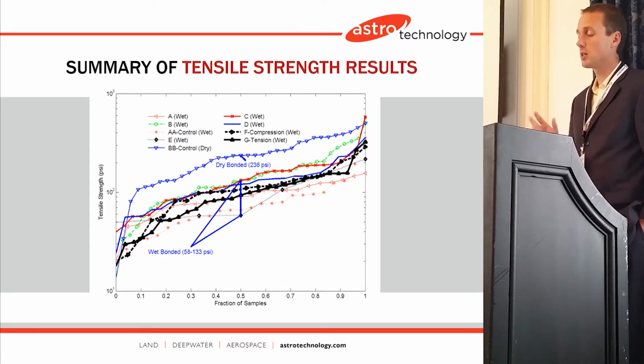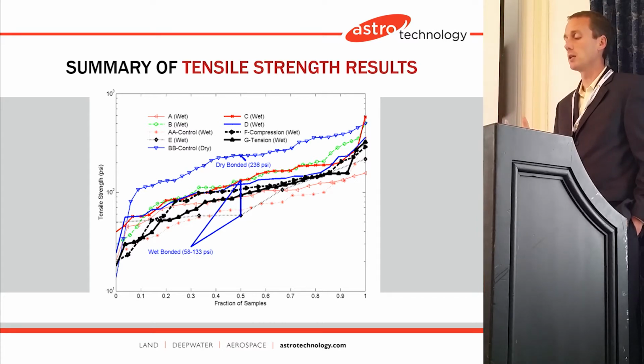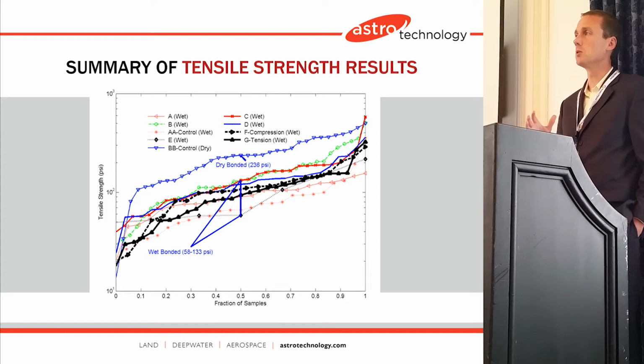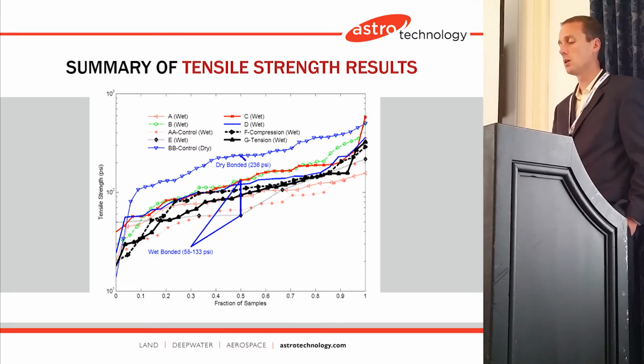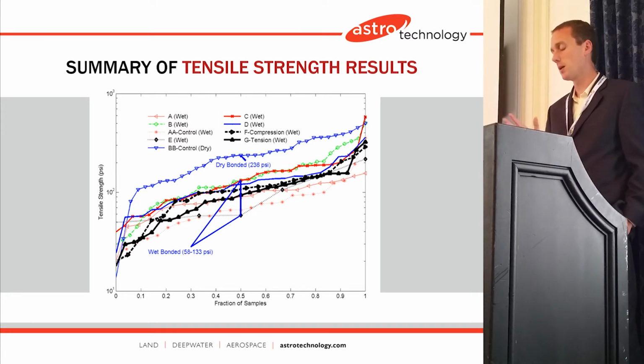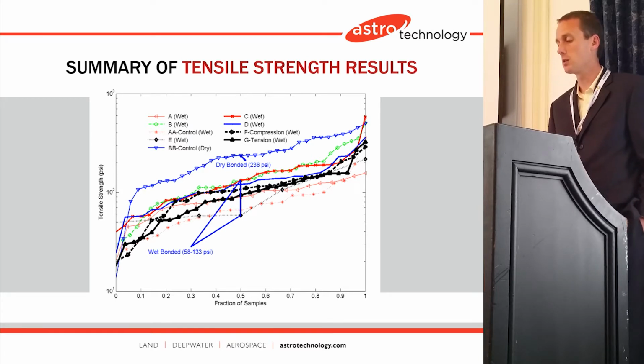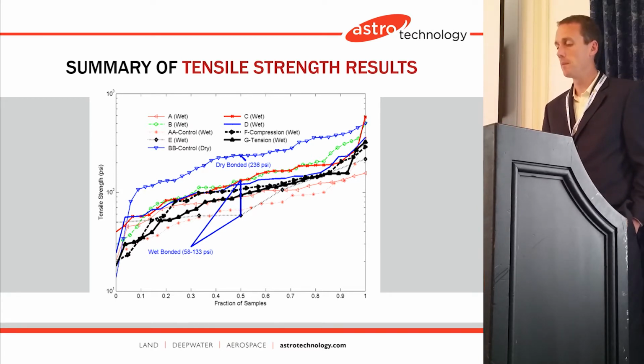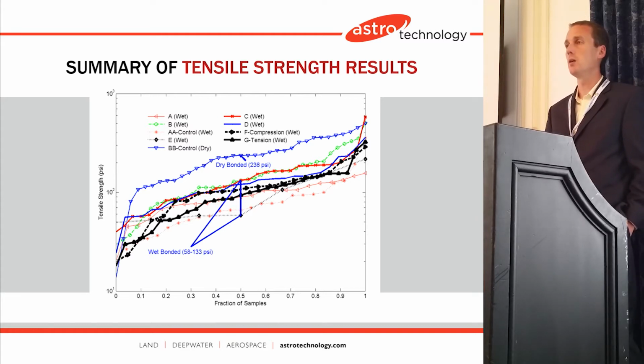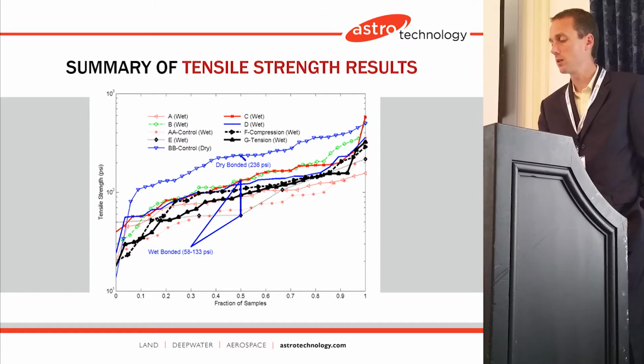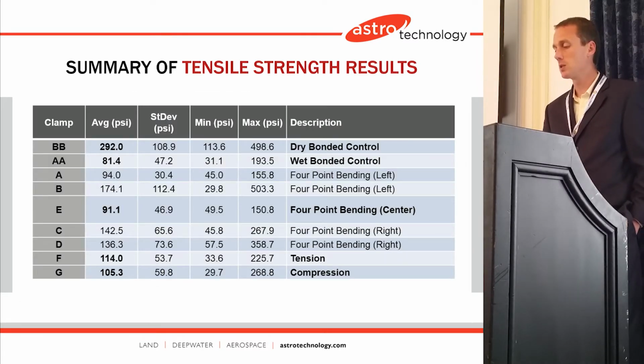We expected the greatest bonding to occur when you apply these clamps in dry conditions. But we also wanted to test what happens when you bond these in simulated subsea conditions. And so the wet bonded tensile strength results were between about 60 and 130 PSI, whereas for the dry bonded, the median value was 236 PSI. And so this gave us better assurance, even after the accelerated aging test, that applying these in subsea conditions post-installation, it's going to have a very long service life and excellent bonding. I'm also showing the table, you have the min and the max. There was also somewhat of a distribution as well.